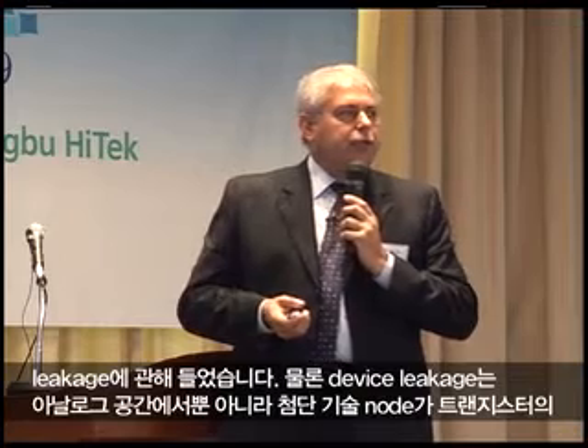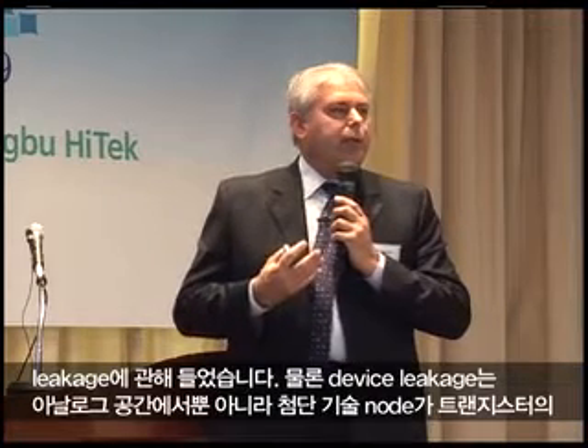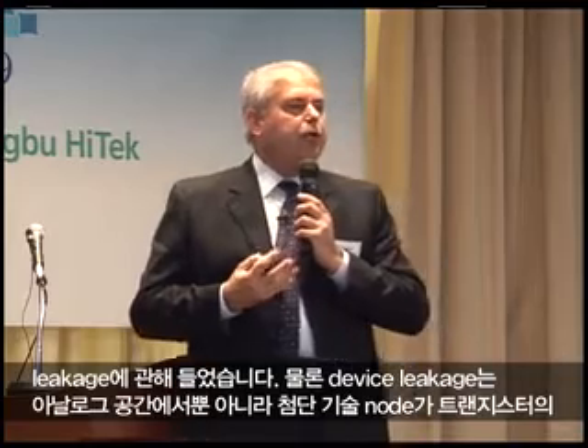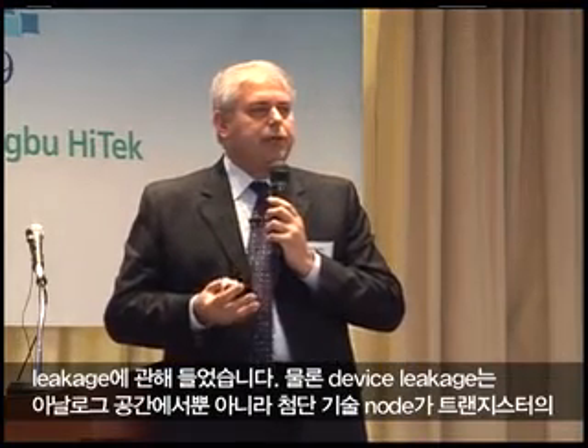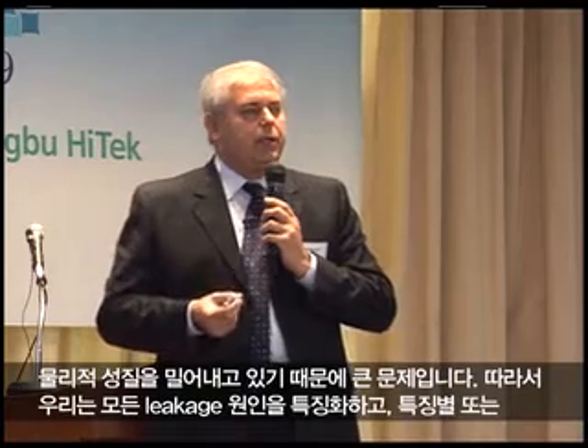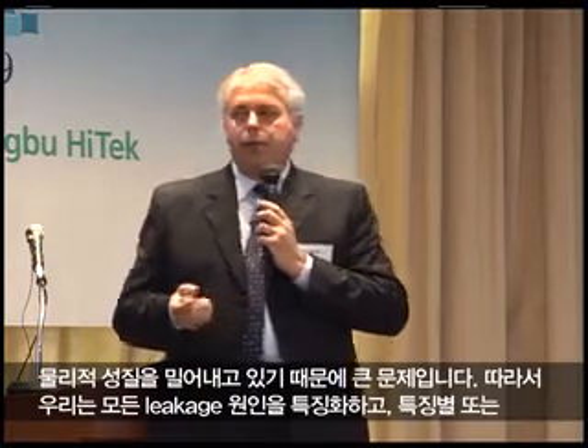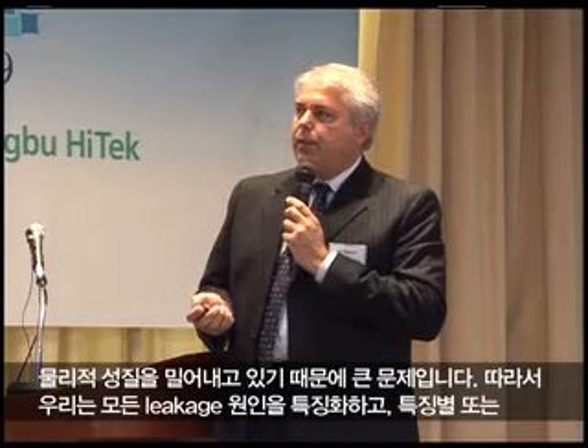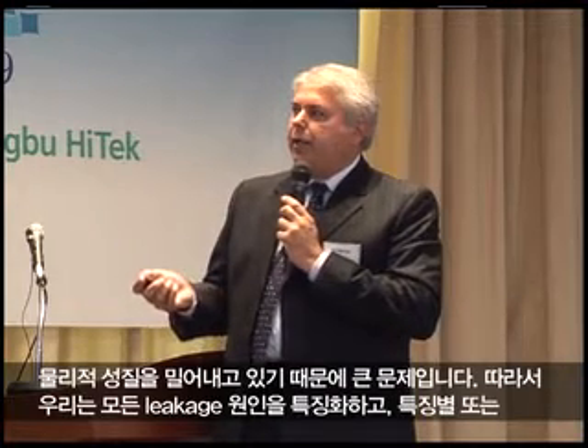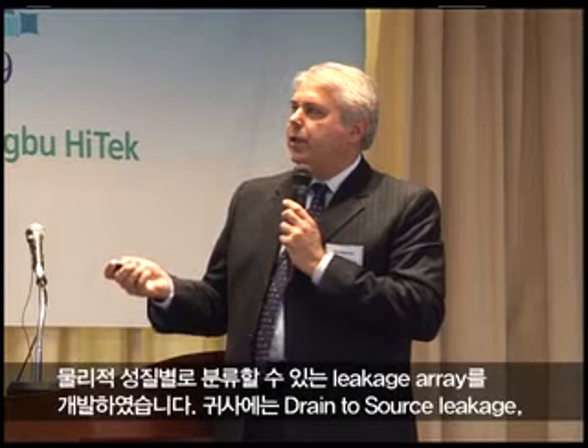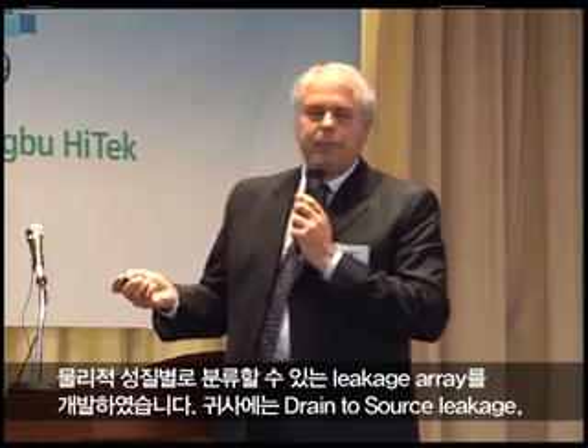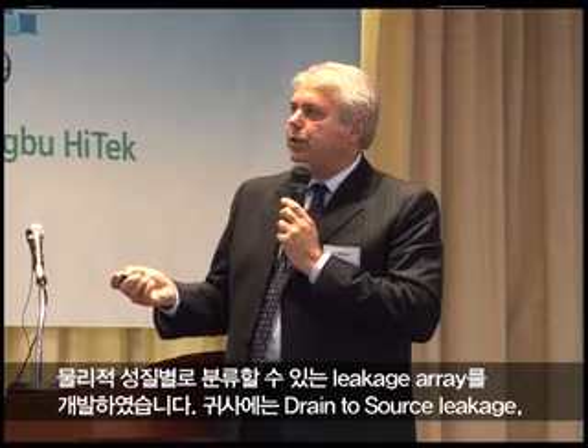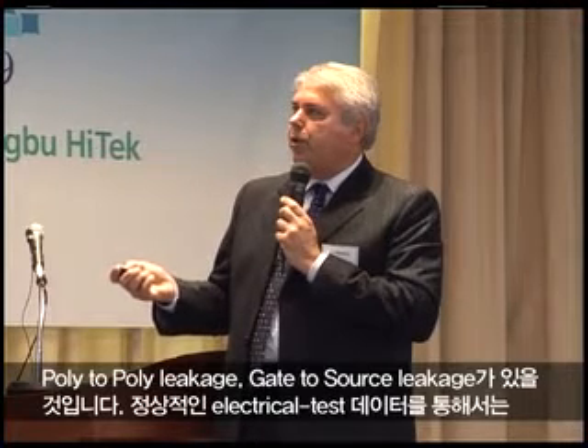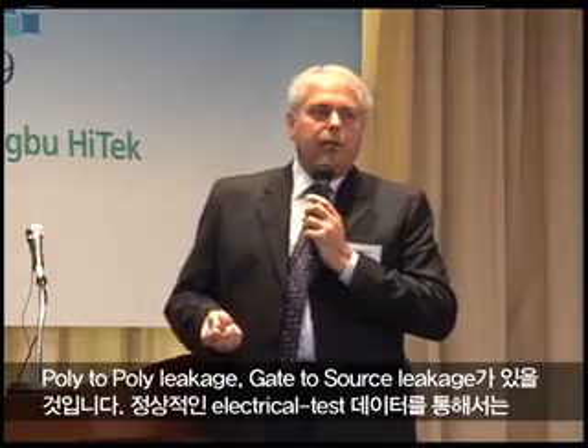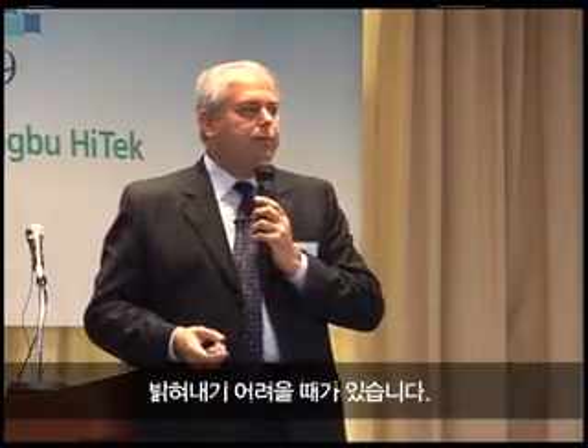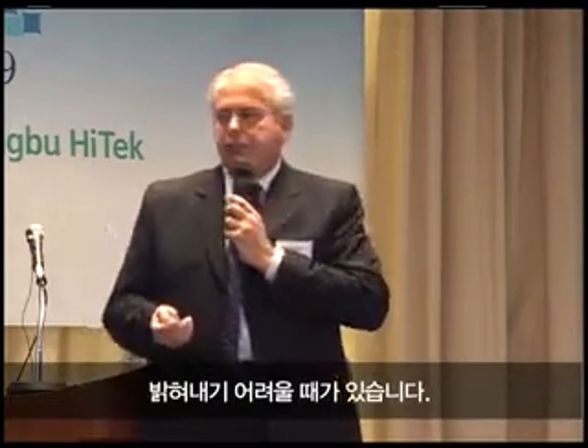We heard earlier about leakage. Device leakage, of course, is a tremendous problem as the advanced technology nodes are pushing the physics of the transistor, as well as in the analog space. So we've developed leakage arrays that can characterize all the sources of leakage and break down by feature or by physics. So you have the drain to source leakage, the poly to poly leakage, and gate to source leakage that are sometimes hard to deconvolve from the normal production e-test data.